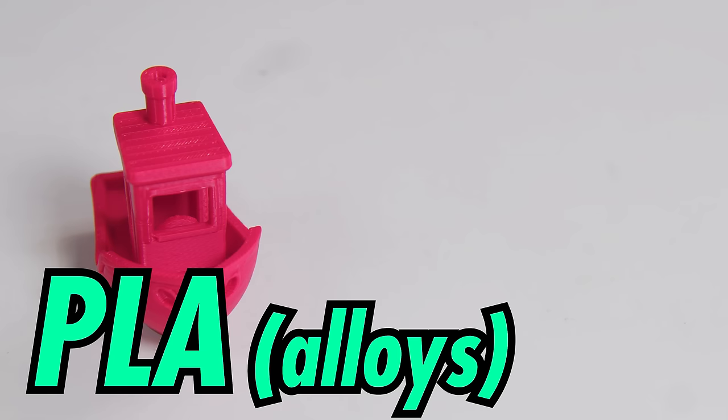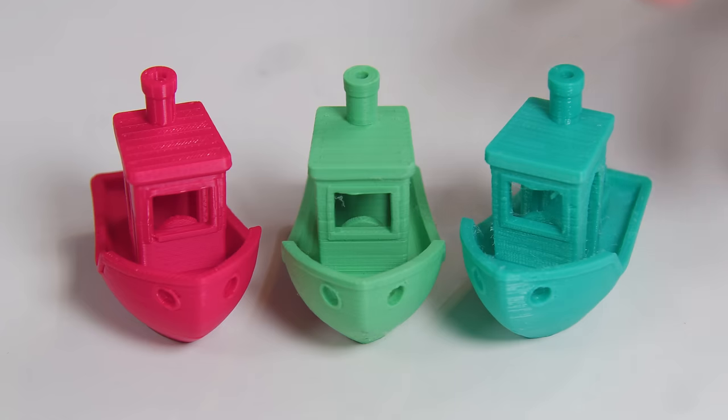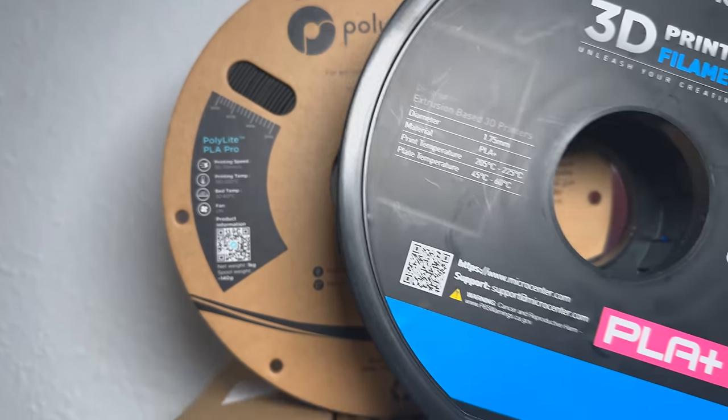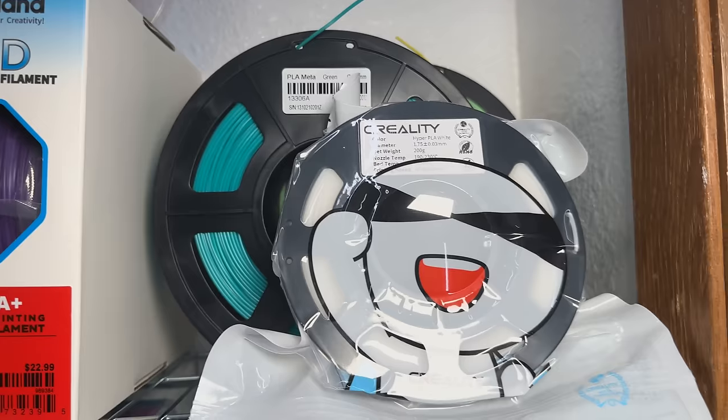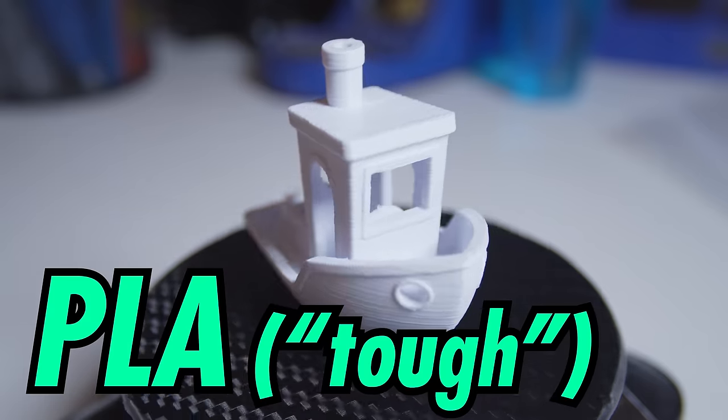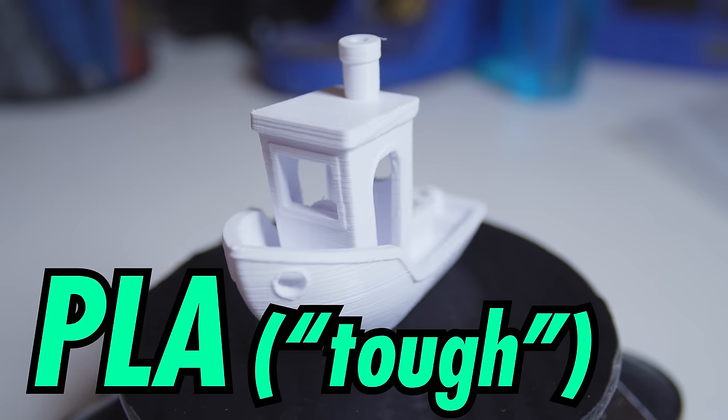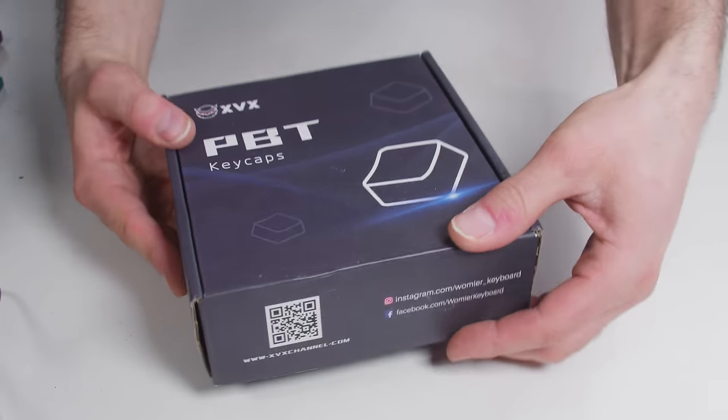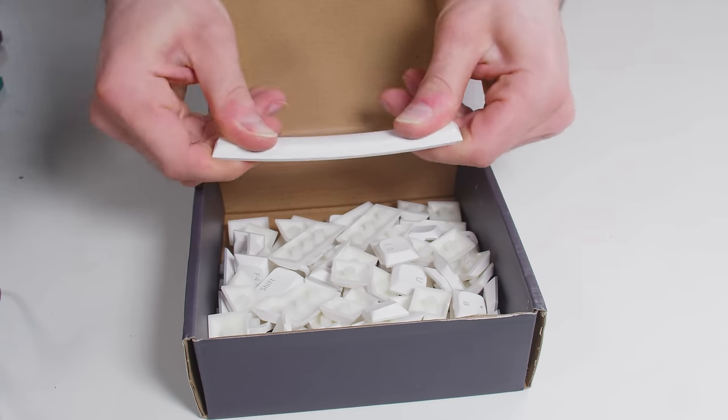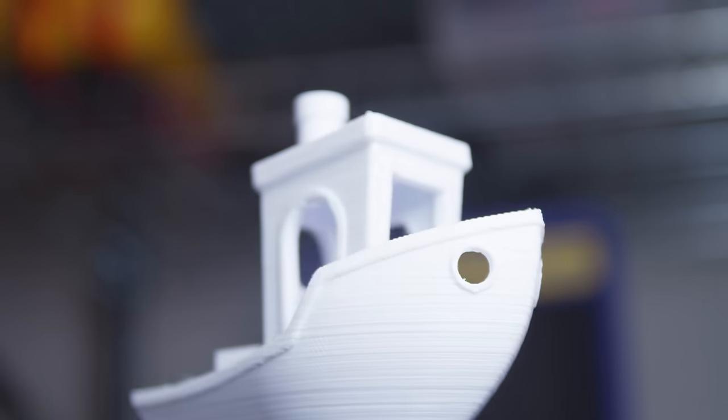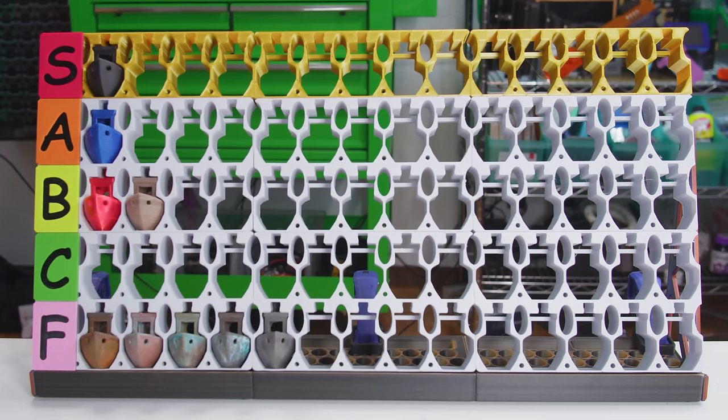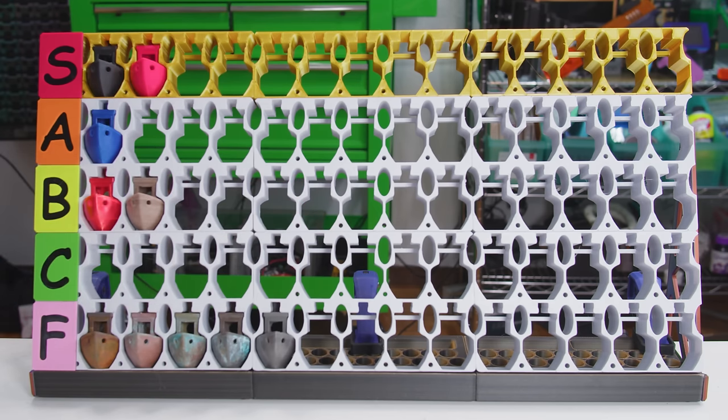These are PLA alloys, PLA improved by mixing in another type of plastic. These are sold under a wide variety of meaningless overlapping and confusing names like PLA Pro, PLA Plus, Rugged PLA, and just infinite more. There are three main formulas. I'm gonna call the first kind tough PLA. Remember, I don't mean spools labeled tough PLA. What I'm talking about is a combination of PLA and polybutylene terephthalate, or PBT. If you're a mechanical keyboard nerd, you have probably seen PBT keycaps. They're incredibly tough and slightly flexible, which is a great set of properties for covering PLA's weaknesses. This wombo combo prints and acts just like PLA, except it resists higher temperatures, handles sharper impacts, and it won't shatter when it's overloaded. Tough PLA is a solid S tier, just a straight upgrade and a superior choice for pretty much every light-duty project.